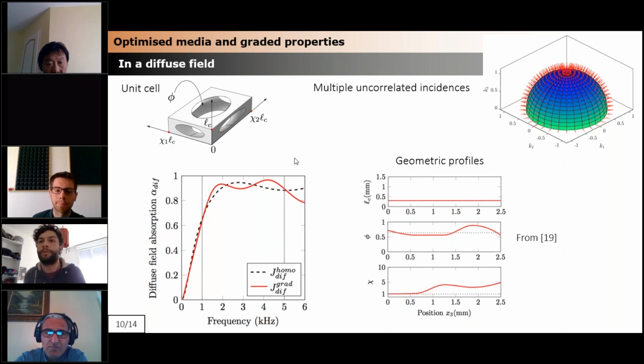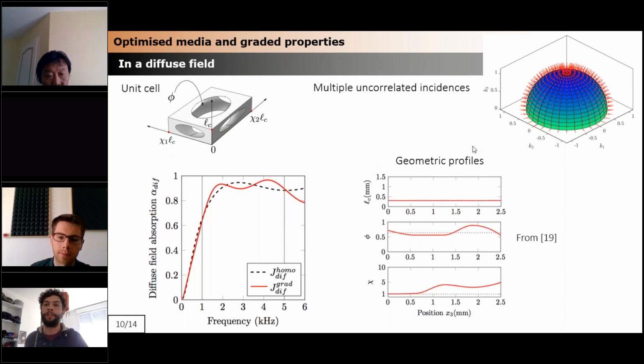You can see on the right the geometric profiles. The porosity is varying, and of course the size of the pore tends to be very small. We also have this factor G, which shows the anisotropic properties. So the stretching of the unit cell may be graded across the depth of the layer. This is also something you can do with the microlattice, because it has anisotropic properties depending on the direction. When you look at it, we have these cross patterns that are, of course, different depending on the direction. So anisotropic cells and their geometric properties can be adapted and optimized for normal incidence and also diffuse field acoustic properties.